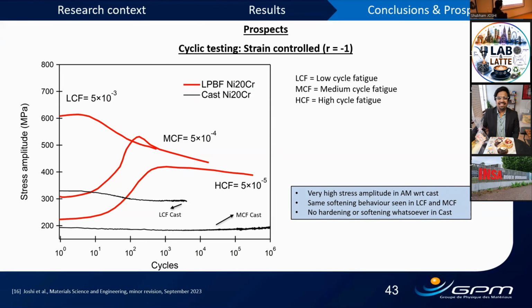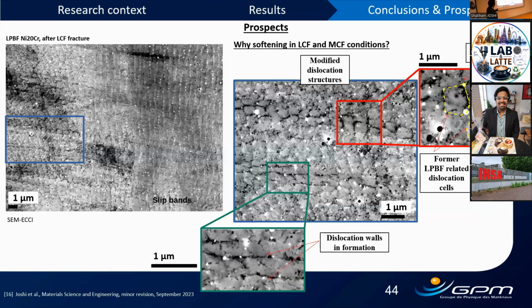We took this part in SEM, and then we saw many, primary is a strong word, but some slip systems which are active, and then there is a dislocation pileup, and this was between two walls. So it seems like the dislocations are somehow going from one part to another, and this somewhat supports our hypothesis on the post-fatigue microstructure. So it looks like they are moving in this direction. They are disappearing at one point and getting differentially stacked up at another point, and this is changing the overall cell size.